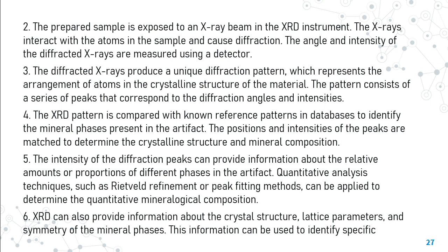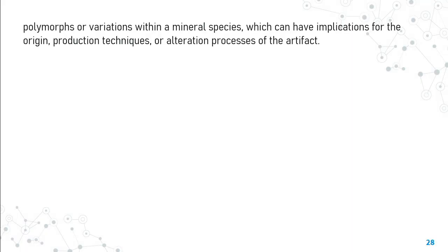in the artifact. Quantitative analysis techniques such as Rietveld refinement or peak fitting methods can also be applied to determine the quantitative mineralogical composition. This process can also provide us with information about the crystal structure, the lattice parameters, and the symmetry of mineral phases. And this information can also be used to identify specific polymorphs or variations within a mineral species.